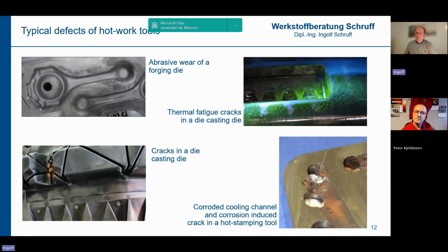Yes. And later on we found that this crack which we have here had been caused by corrosion starting from the cooling channel. And this is the highly stressed area of the hot stamping tool. Here, the sheet metal flows over this corner, so we have a lot of stresses in this section. And this was probably a kind of stress-induced corrosion, and that corrosion crack grew in the direction of the working surface, and later on the water leaked out. Yes, and nowadays in die casting we have similar activities.